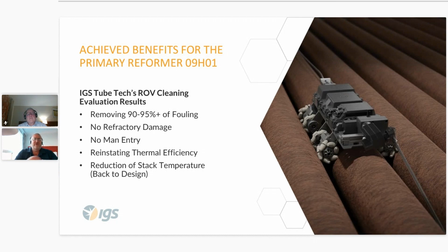So it removes somewhere in the region of about 90 to 95% of all fouling on the coils or the banks, whichever you want to call them. It doesn't damage your refractory, so please don't go down the route of, oh, we'll lose our refractory, it'll get damaged. It doesn't happen. In fact, just using water as our motive force means that your refractory isn't subjected to any harmful chemical, which can damage the actual adhesion which holds the refractory together.